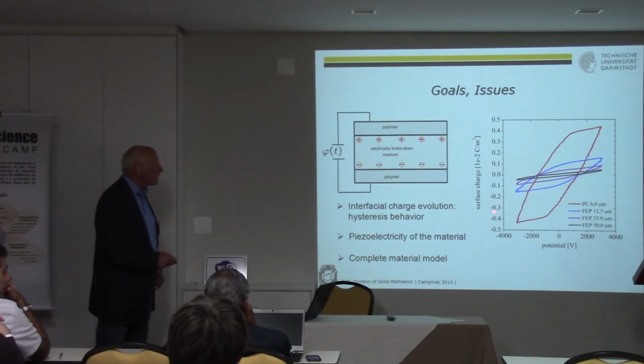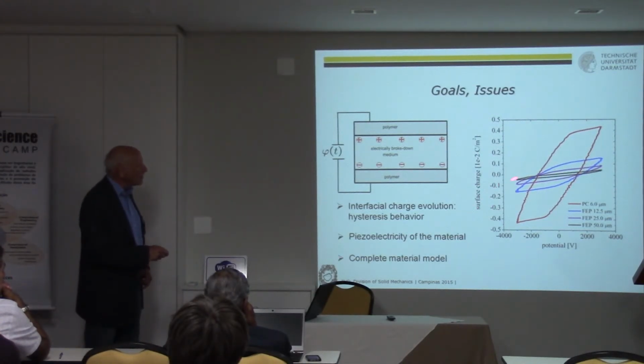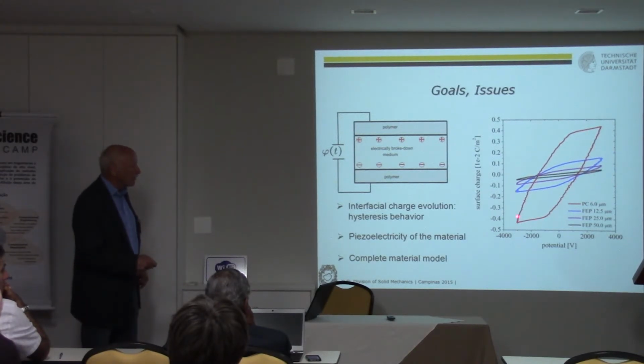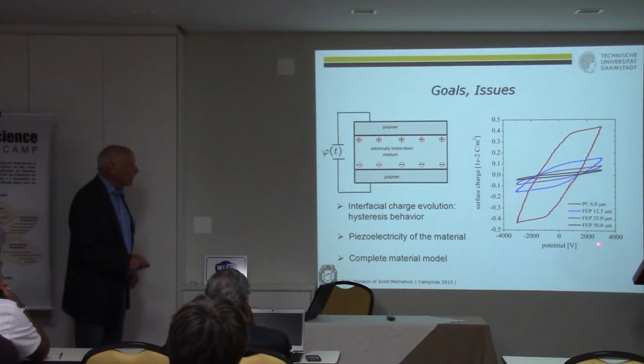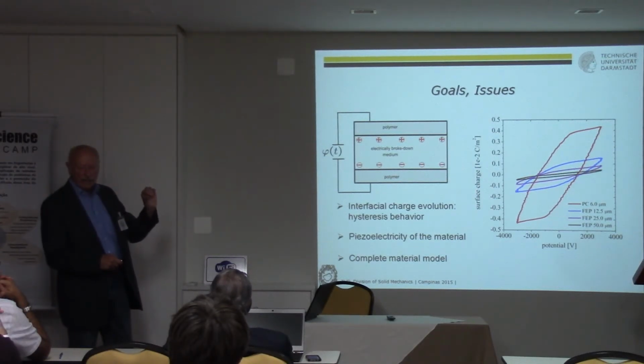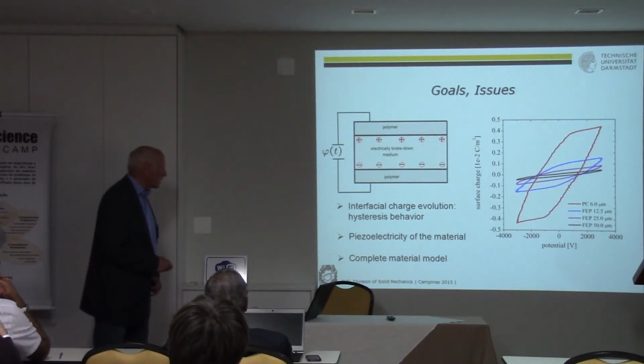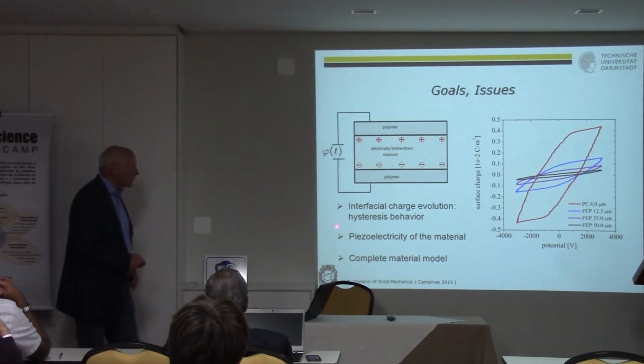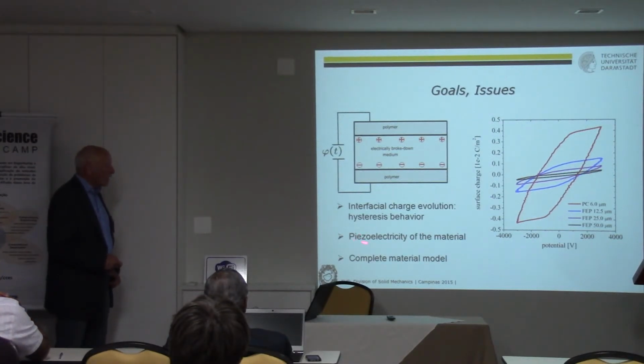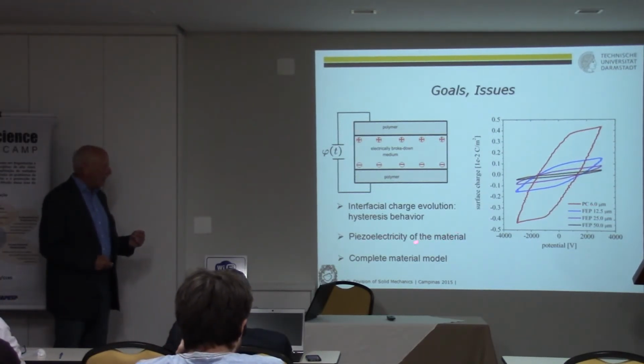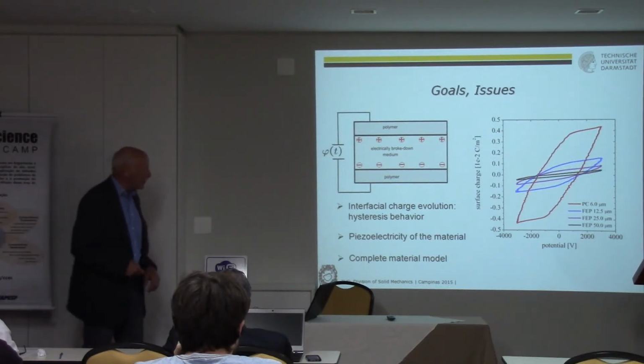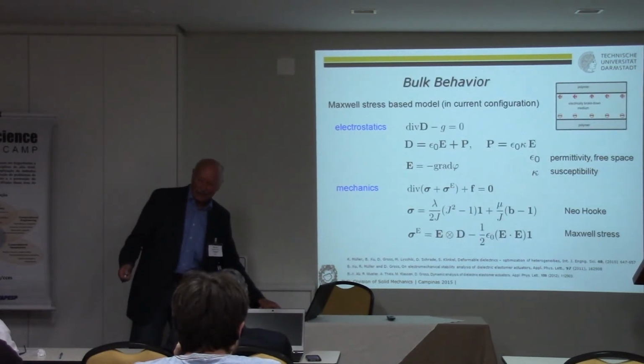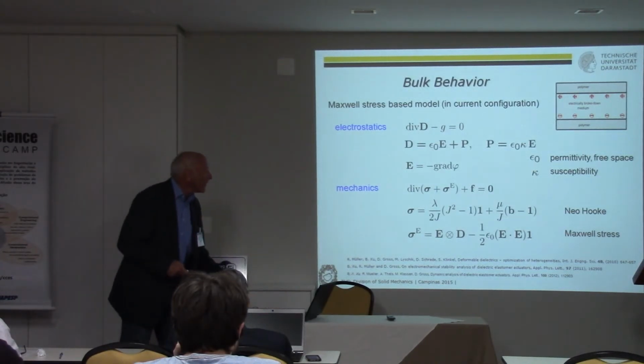what you can measure is the surface charge, but you see a hysteresis effect. Here for these micrometers is in this case the thickness of the sheet. And what is of interest, how to determine the piezoelectricity of the material, and is it possible to derive a complete material model, and this is possible, and it works very well. And I show only, if you allow me, how it works.